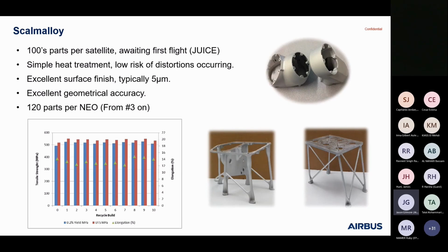In terms of the surface finish I mentioned, we've got excellent geometrical accuracy when we 3D scan them. I can't remember the numbers, but about 98.5% of all the geometry was within plus or minus 0.2 of a millimetre. Anyway, hugely geometrically accurate, which for RF parts is very, very important, not so much for mechanical brackets.